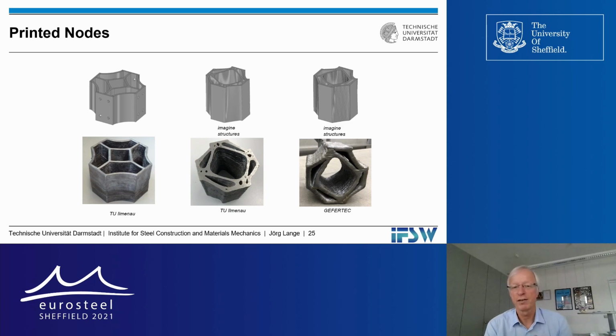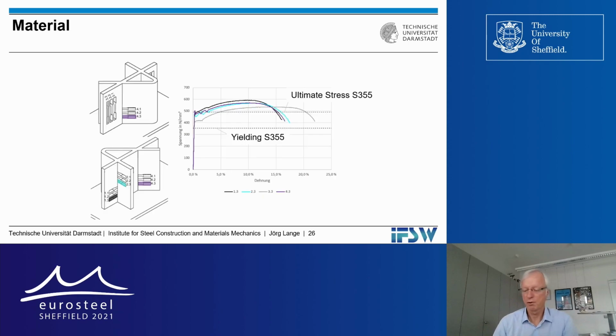In the center, on the right-hand side, you have different moments and different normal forces, different shear forces coming from the 4 members. So you can react to this by different filling inside, and in the final step, of course, 4 plates can have different angles to each other, and you make these nodes, and that makes it quite easy to bolt straight beams to them. In this project, we also did some material tests.